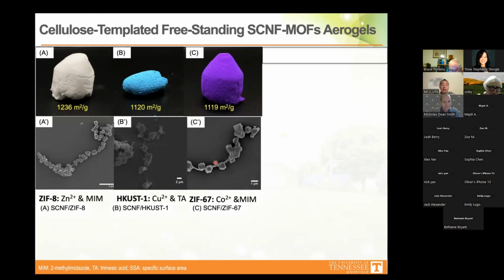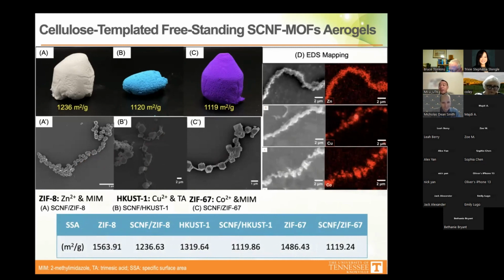So that means the nanocellulose can work as a really good template for the metal organic framework to hybridize. Okay, so here is a picture to show you we want to verify the metal organic framework is dispersed along with the fiber. So we use energy dispersive X-ray spectroscopy to map the distribution of the metal ions.